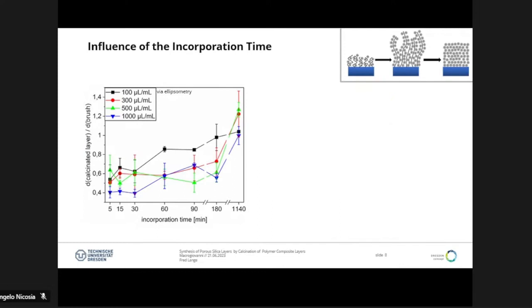In addition to that, I also studied the influence of the incorporation time. So I used different concentrations of the particles and different incorporation times. And as you can see, the thickness ratio between before the reaction and after the reaction rises with time, which is, of course, what you would expect.